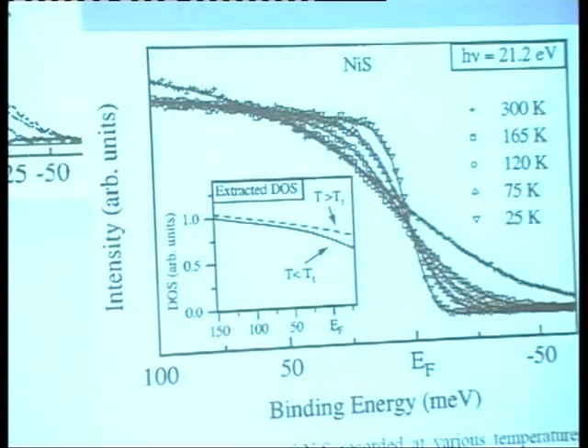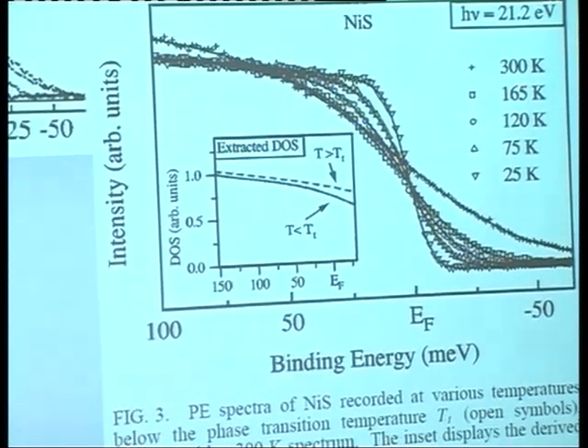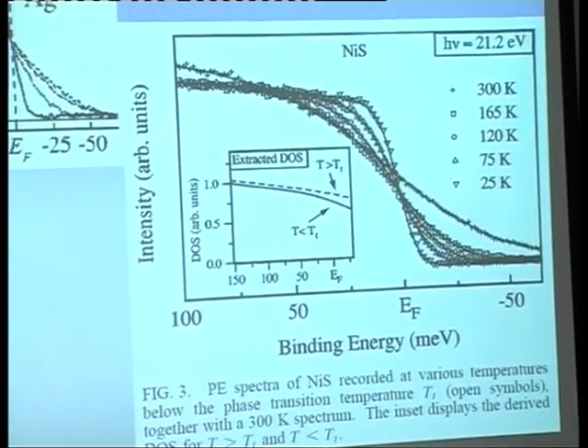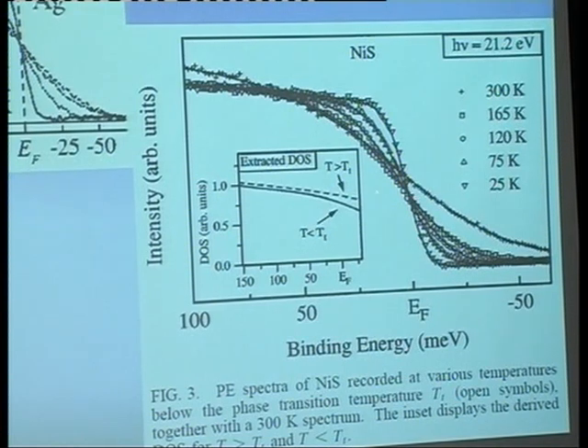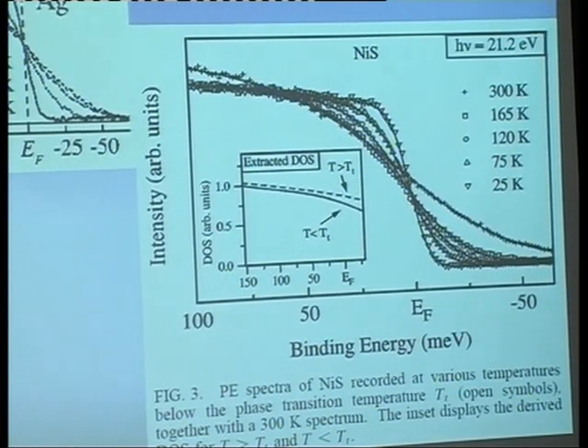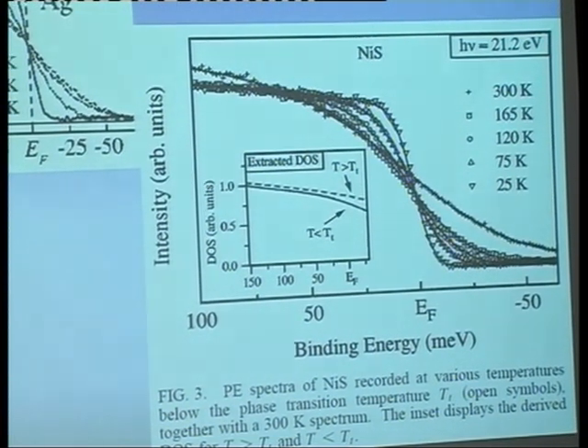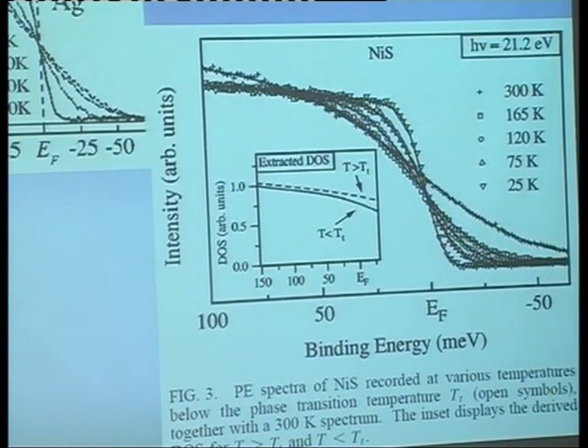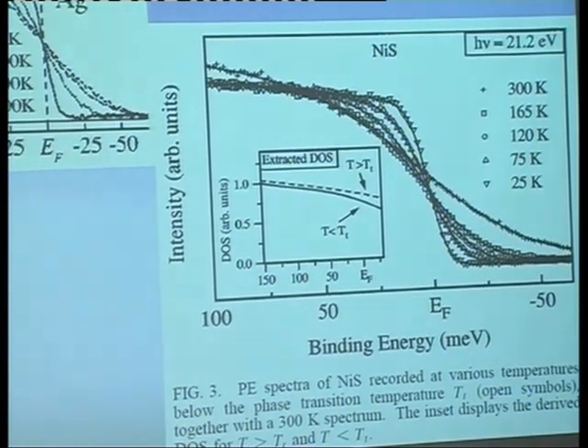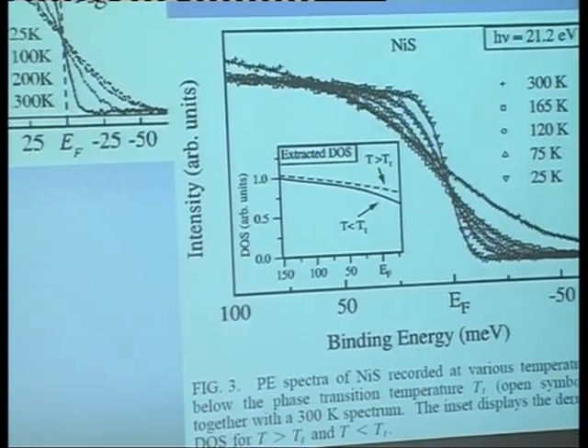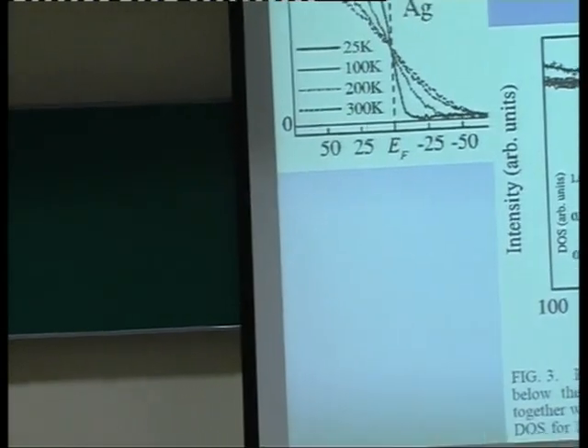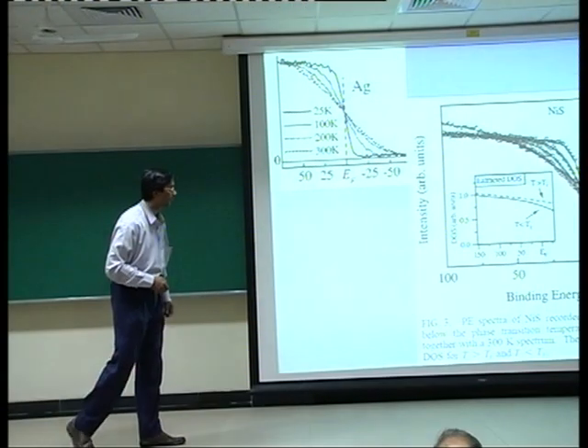If you look at the rest of them, nickel sulfide, all below the transition temperature from 165 to 25 Kelvin, you can see that all of them go to the same point exactly the way it happens. There's this depletion of states and states that are building up, telling me that there's actually continuous spectral weight right across, both in the single particle and normally at equal to 0, what will be the particle addition spectral part.